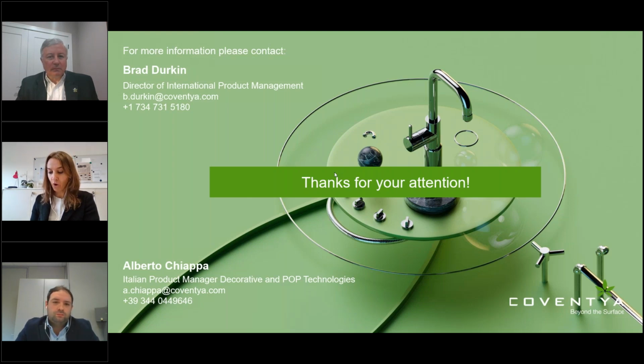Must we use the Tristar post-dip HM for all the applications? No. The application for steel is important. It's very important. Sorry, Brad. It's important for the inner tube. Yeah, I mean, again, Chrome 6 is known to passivate unplated surfaces of steel where you don't get the corrosion. When you switch away from a Chrome 6 to a Chrome 3, there's more tendency for corrosion in unplated areas. So the inside of tubular work and furniture, steel surfaces exposed, you need to add protection. And that's where the post-dip HM comes into use. So I don't think you'd want to use it unless you've got tubular work. As Alberto said, it's not for every application, but for some. Yeah. Okay.